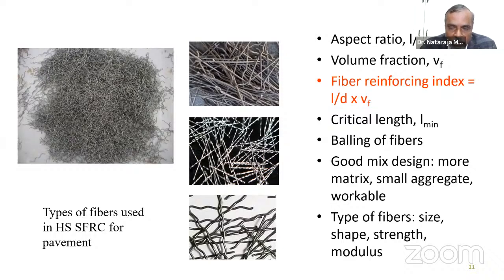But for the first time, if you see in the literature, the volume fraction and the aspect ratio were both considered together as a multiplication factor. And we have introduced one concept called the fiber reinforced index, L by D into VF, for the first time. So this concept of fiber reinforced concrete has been introduced, and there are several papers which we published almost 20 years back on this concept. And today it is the fiber reinforced index concept from the point of concrete mix design, where the importance of both aspect ratio as well as the volume fraction of the fiber are considered in the design of steel fiber reinforced concrete.